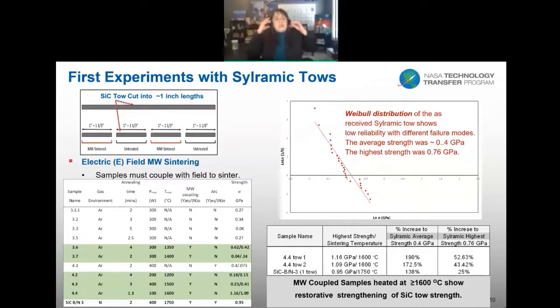One of the things that I noticed is when you see silicon carbide in microwave sintering, a lot of times they use it for nanoparticles, but I see a lot of people using high power, and I've never understood why, because we always coupled at low powers. We hardly ever used the power. I think we did it one time where we went high power, beyond 400 watts, into the kilowatt power range, but then I started having thermal runaway, and just shut it off.